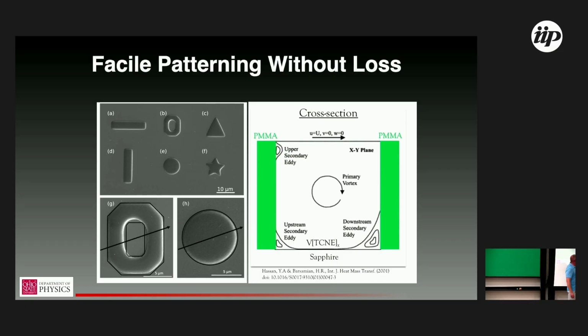But I think this is something that is important to emphasize. So this is adapted from this reference here, and this is highlighting the fact that, contrary to most thin film synthesis that we're probably familiar with, where you have a reasonably good vacuum and more or less directional deposition, this is at pretty high pressure, torr or so, and so gas flow dynamics actually matter.